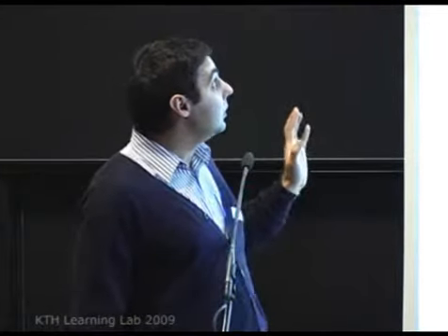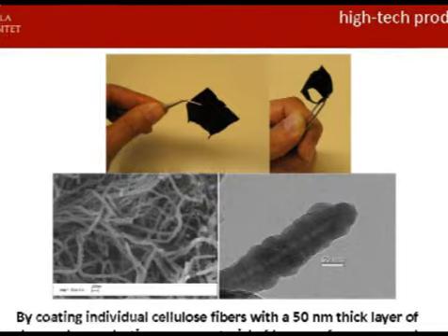And these applications include many different ion exchange membrane solutions in which you can just take the paper, use it as an electrode, dip it into a solution from which you want to extract something valuable. So you put the paper in the solution, you apply current, the ions are being taken up inside the paper, you remove the paper, put it in another solution, apply current of opposite magnitude, and by that release, so one can extract inorganic ions, one can extract organic ions, and we are working very hard to extract biomacromolecules.